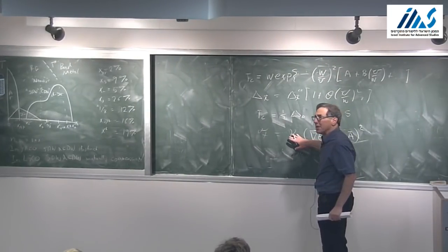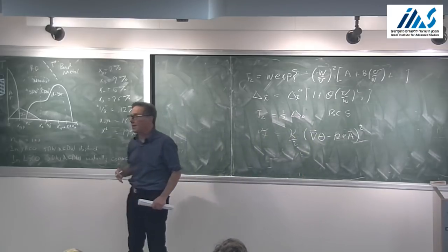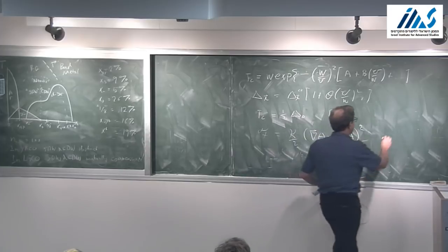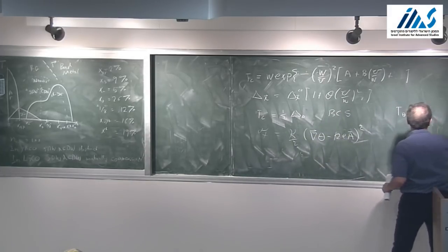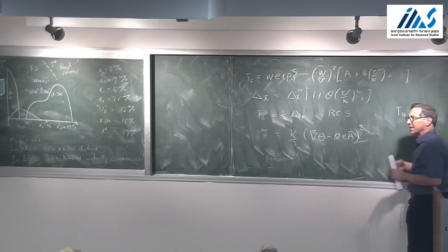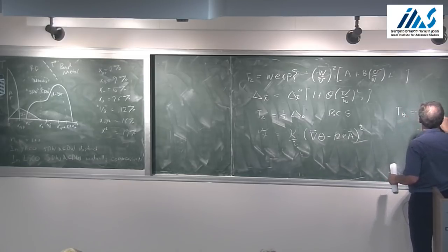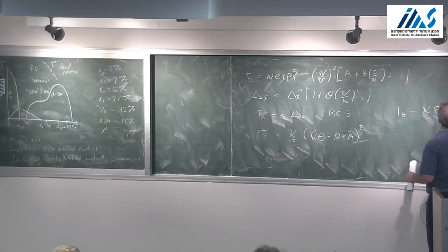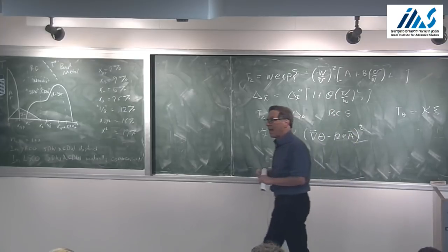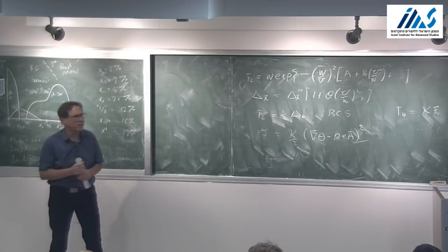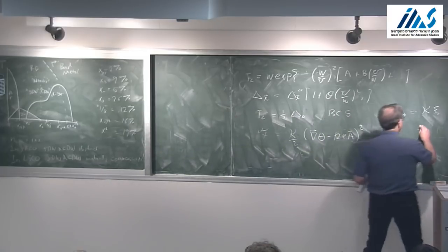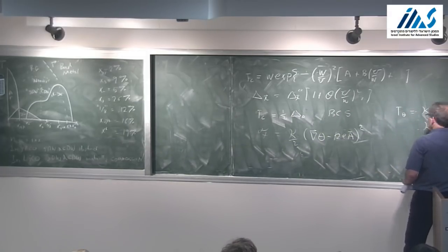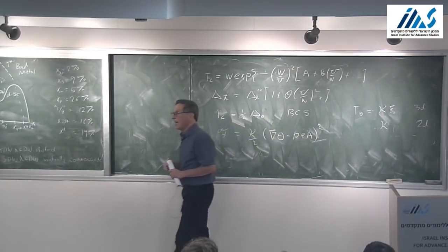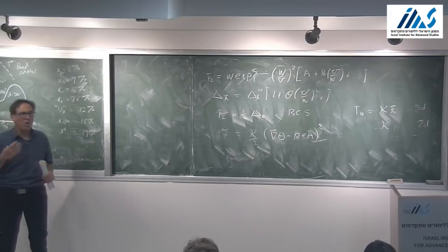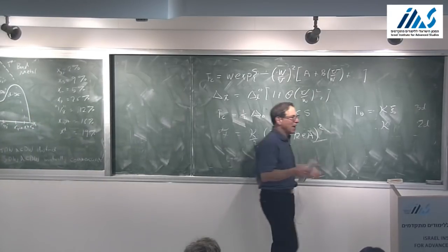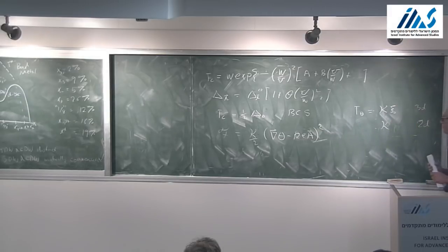In 3 dimensions, kappa has units of energy per distance. So to make an energy out of this, let me call it T theta, I have to take kappa and multiply it by a distance, and the only reasonable distance in this problem is the superconducting coherence length. So that's some energy scale that characterizes classical phase fluctuations in a 3-dimensional superconductor. In a 2-dimensional superconductor, kappa has units of energy, and so it directly tells me about some temperature scale at which phase fluctuations by themselves would proliferate and destroy the superconducting state.